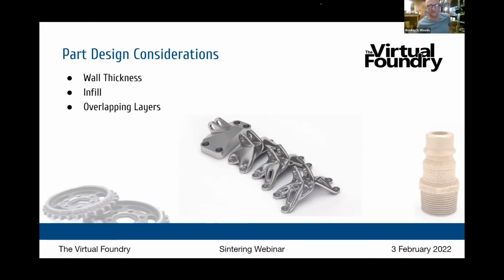Right. This is something that we're discovering. So as you're printing this, the polymer with the thermopolymer and the metal together, an interesting thing happens when you try to force a large group of spherical particles through a single space. That is that the larger particles get pushed to the center. So each print line winds up having more large particles at the center of the print line than it does at the edges. And this normally isn't generally a big problem unless those lines don't slightly overlap. What'll happen is if they don't overlap slightly, they'll start to delaminate during the debinding process.